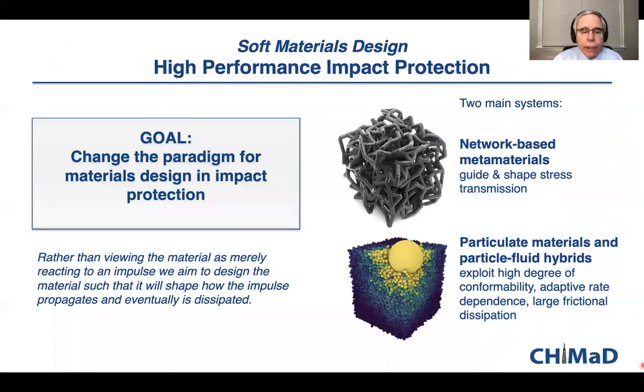The high performance impact protection group is looking at novel ways of channeling energy associated with impacts to regions of a helmet or another device that avoids the problems with the impact being absorbed by a human, for example. And they're doing this using two ways. One is that they're designing new network materials using computational methods, and also looking at the interaction between a larger particulate and a fluidized bed where you have particle and fluid in a substrate on which this particle impinges.